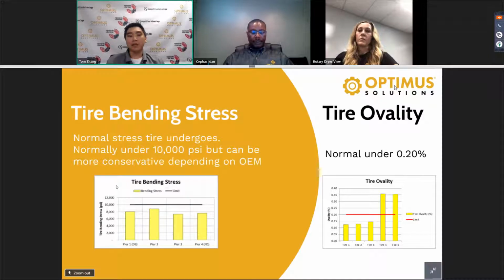Their tire bending stress was already about 10,000 at 4 inches. And at 3 inches, they were in the 20,000 range. So it was quite high, so high to the point I looked at the literature for their case. They're right around 20,000, and there is a limit where around that time, if one inclusion happens, they will crack the tire and fail it. So that's an example of how the conference calls can really come in handy, because without that information from the customer about how much they'd ground, you wouldn't know otherwise, right?